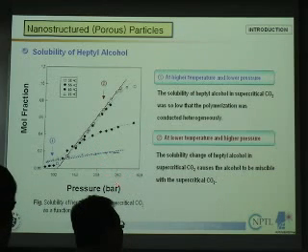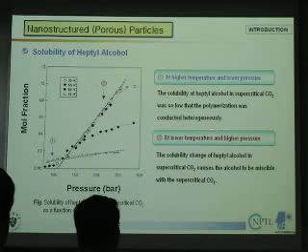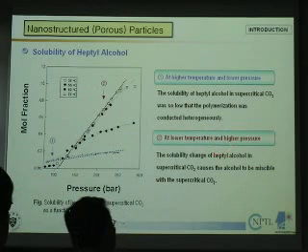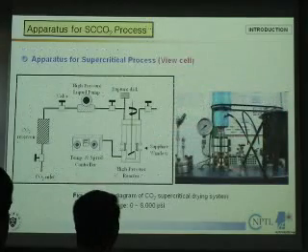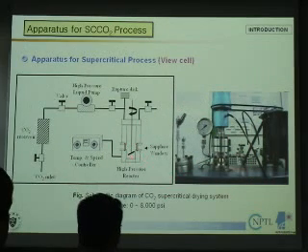That means you don't need to worry about the solubility of that heptyl alcohol in the supercritical fluid. And then during the reaction, just adjust the temperature and pressure. Now the mode is moved into the extraction stage. So this is the process we apply to make that kind of particles.